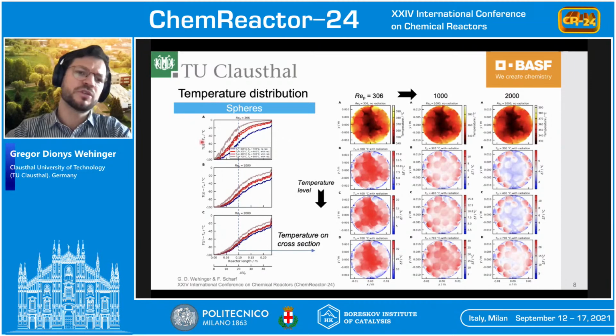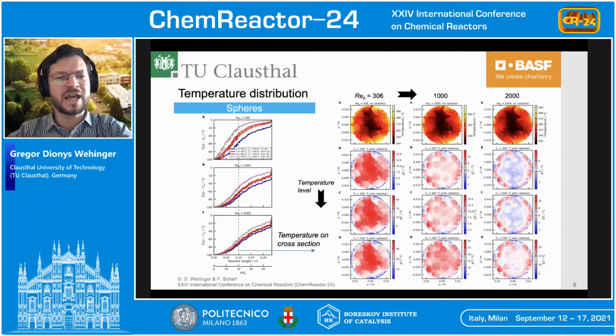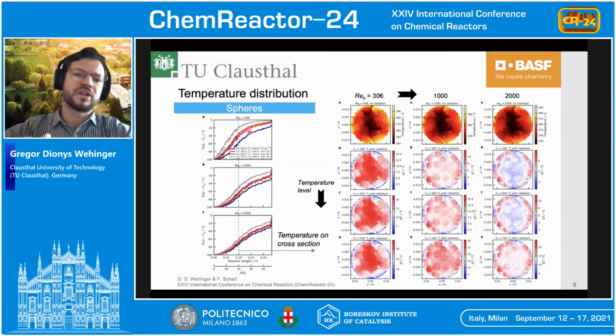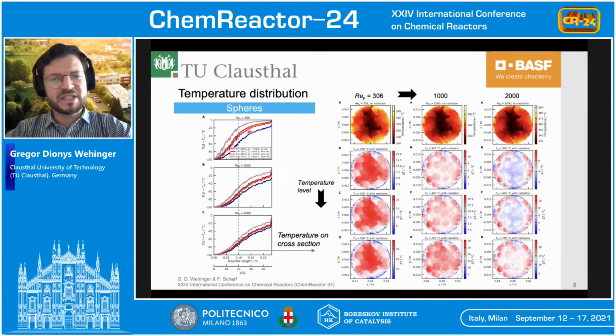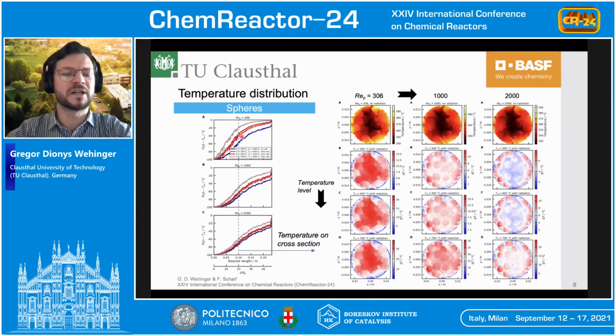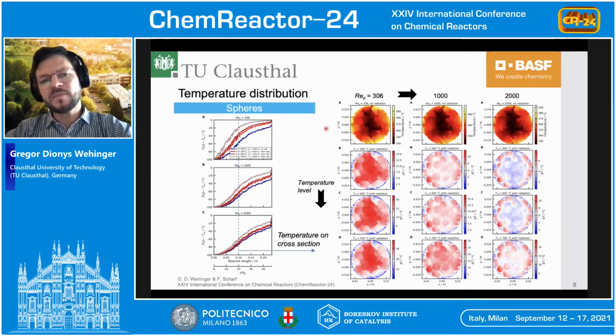So on the left-hand side, I show you the 3 different particle Reynolds numbers. Now the axial temperature profile from the CFD simulations. Blue is the scenario without radiation. And then the reddish ones are the scenarios for the 3 different temperature levels. So basically, and this is what we assumed, we have a stronger effect of thermal radiation the higher the temperature level is, obviously. This is the Boltzmann law included. But the extent depends on particle Reynolds number, although thermal radiation is independent of the velocity. It interacts with the occurring transport phenomena. And this is also what we can see here. So here, it's a cross-section on this dotted line for the 3 different particle Reynolds numbers.